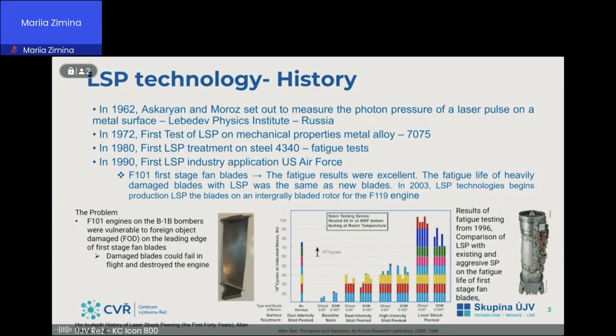Therefore, in 1996, a lot of fatigue tests were performed on base material from the blades. As you can see in the chart, on the base material with an EDM artificial notch, and on the material after classical shot peening, which you can see in the middle, and with the LSP technology, laser shock peening. And as you can see, the fatigue results were excellent for LSP.